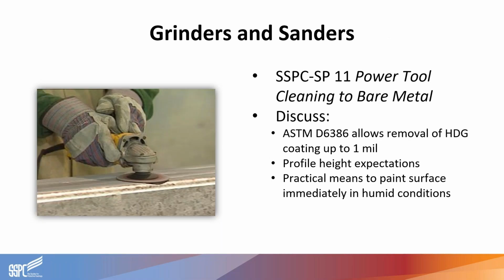Another method that is available to roughen the coating is the use of grinders and sanders. The details are prescribed in SSPC SP11 for power tool cleaning to bare metal. So that's going to provide a profile of at least 1 mil. So if you're looking to achieve significantly greater profile heights, you may want to consider a practical test to determine whether you need to be looking at abrasive blasting to achieve that instead. When performed carefully and with low force, this can be a suitable preparation method for many coatings, but it is possible to damage or thin the coating if someone goes a little crazy with the power tools.